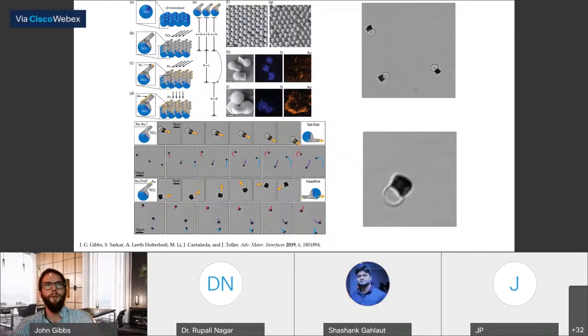And so the two that we focused on was just putting it on the very end. So if you look at figure C here, what we did is we grew the tail just like the other slides I was showing you, and then we put the gold just directly on the end. So we kept the angle the same, and we deposited gold at the same angle. Or what we did for D is we took the substrate after the deposition of TiO2 and deposited directly down, so it sort of coats the sides of these tails here.